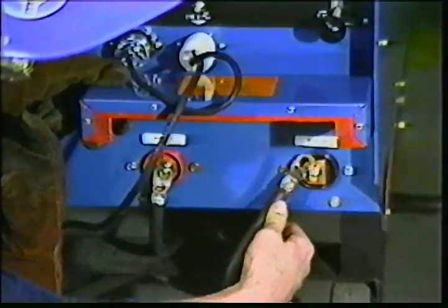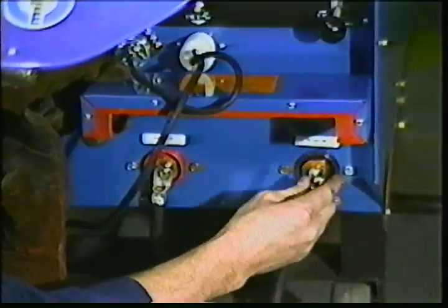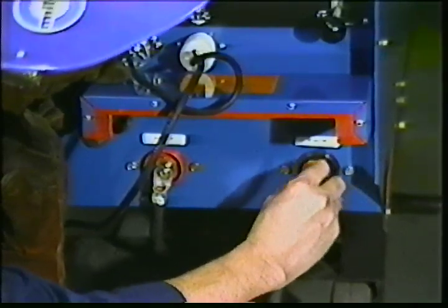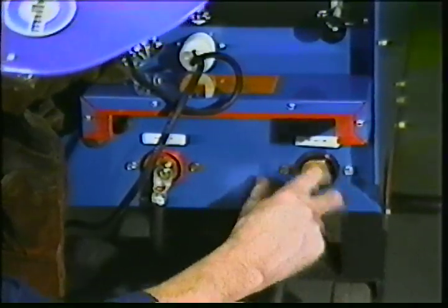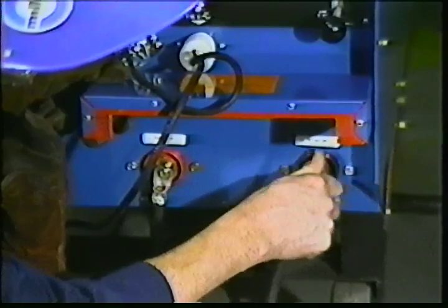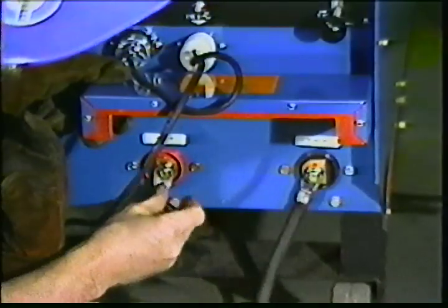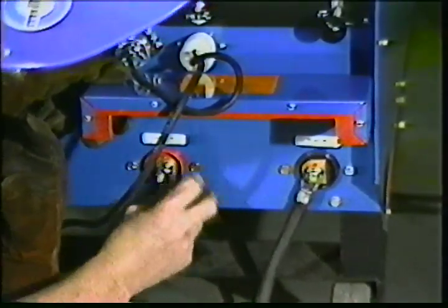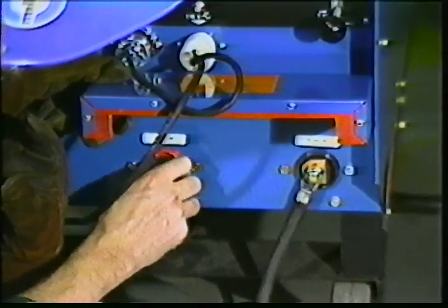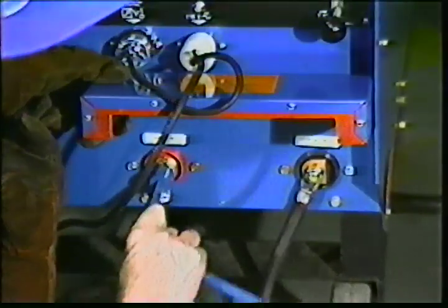High ropey beads can be caused by improper parameters. In this case, the electrode was hooked to the negative terminal, resulting in straight polarity. The electrode and work lead are switched for reverse polarity connection. Materials 16 gauge and heavier are most often welded with reverse polarity for deeper penetration and good appearing beads.